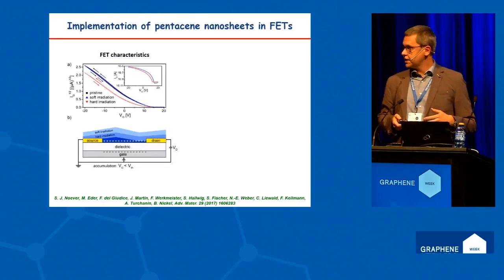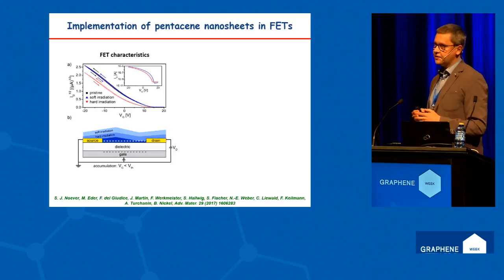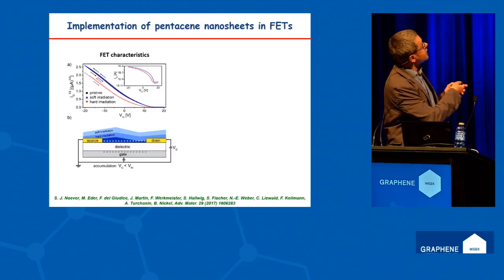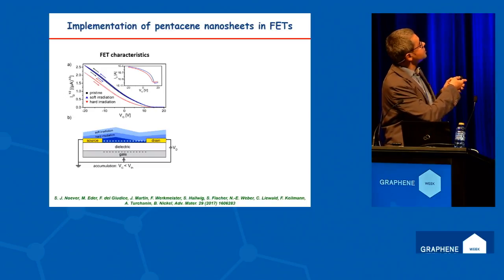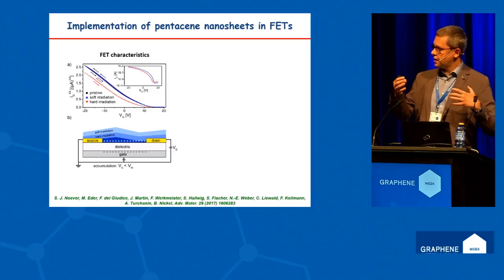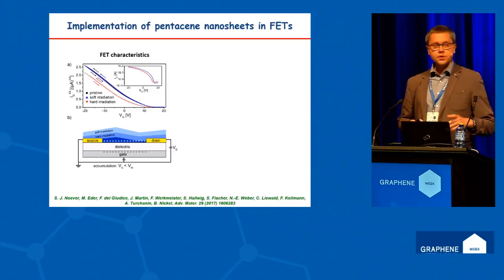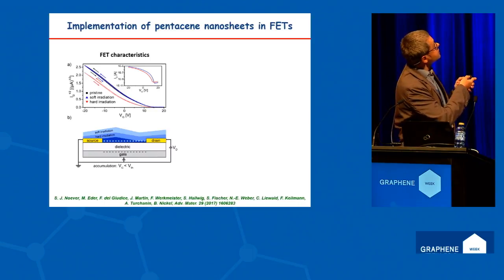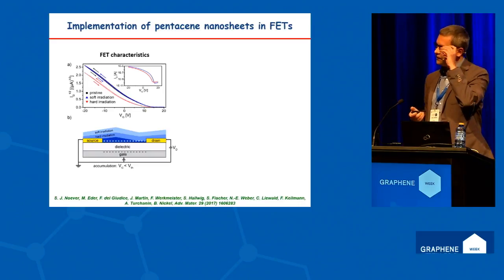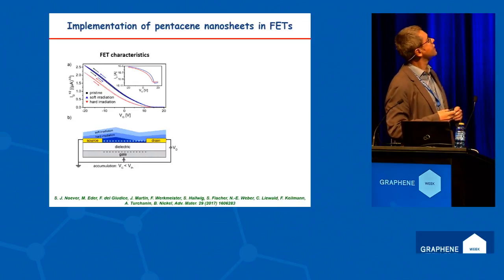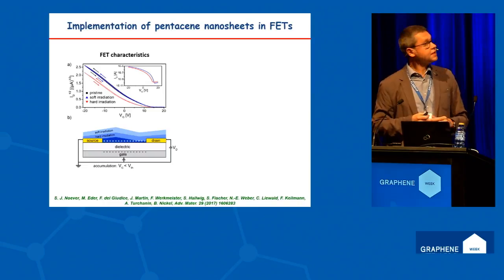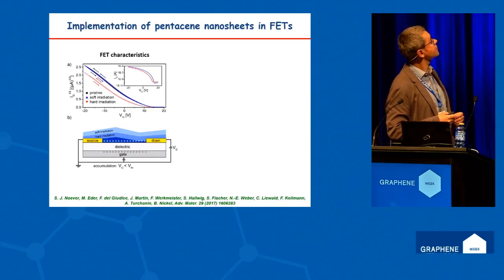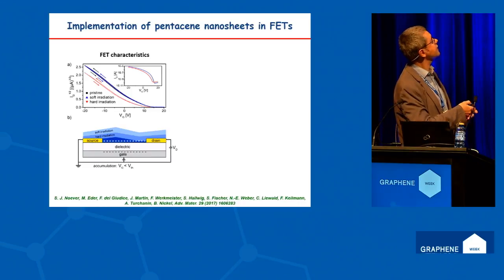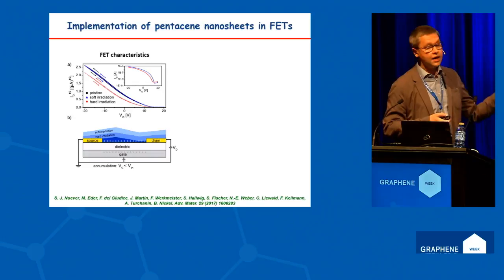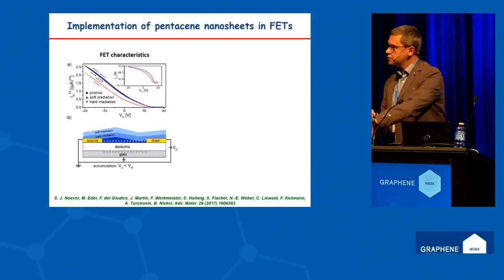And this is, of course, the interesting question: how well does this organic semiconductor work in devices? This is a comparative analysis of one pentacene sheet, which was strongly cross-linked into the depths, and a pentacene sheet which was cross-linked only on the surface. And you can recognize that with this surface stabilization, there is practically no difference in field effect characteristics between the pristine pentacene sheet and the pentacene sheet produced by this cross-linking and transfer, and only if you go to higher electron energies and higher doses do you introduce some damage.